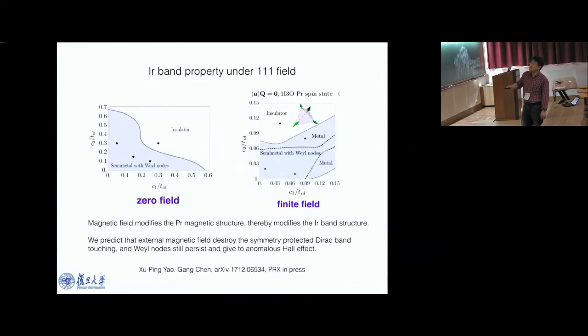And this is the comparison between the band structure properties of the conducting electron without magnetic field and with magnetic field, for field along one direction. These are not properties in the same parameter regime. In the whole region from 0 to 0.6, this is all semimetal, but for this plot, only 10% of that is semimetal. So imagine the system is here, then you apply a field. You can drive the system from a semimetal to an insulator, so you can have a metal-insulator transition tuned by an external magnetic field. That means you can use this as a switch. Originally it's a metal, and if you apply a field, it becomes an insulator. So you stop the current flowing by applying a magnetic field.